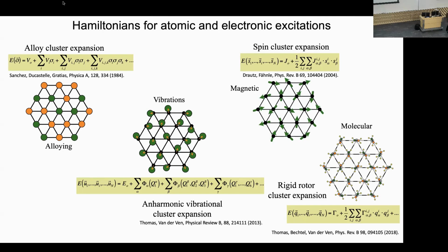And then the energy of the crystal, depending on how these atoms are arranged, can be expanded as a polynomial expansion of these occupation variables, where you've got pair interactions, so nearest neighbor, second nearest neighbor, third nearest neighbor, and so forth, triplet interactions, and so forth. And then you have these expansion coefficients. And this is something that we can fit to expensive DFT calculations. And this kind of an expansion can then be extrapolated to many, many more excitations that we could sample in something like a Monte Carlo method. So this is the kind of workhorse of interpolating and extrapolating expensive density functional theory calculations to calculate thermodynamic properties. And this is just the simplest one.